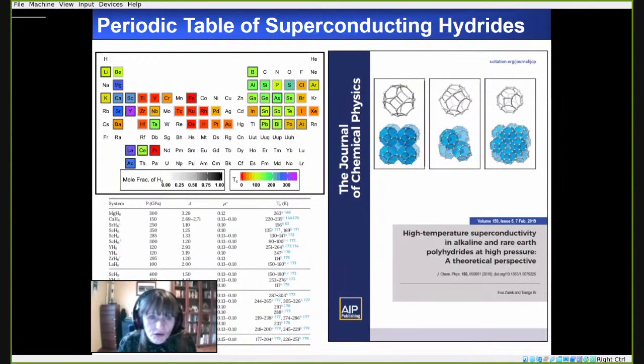So here I show also a recent review that we have written, taking a look at the periodic table of superconducting binary hydrides. The types of crystal structure prediction techniques that I have just discussed, as well as many other groups, have theoretically predicted the types of binary hydrides that might be stable under pressure, and then used BCS theory to estimate their electron-phonon coupling and their superconducting critical temperatures. And what we find for the binary hydrides is that there are two regions within the periodic table that have particularly high Tcs. One of them, as I've alluded to earlier, is in the region of the p-block elements around sulfur, selenium, tellurium. And the other one is around the region of the alkaline earth and rare earth hydrides.